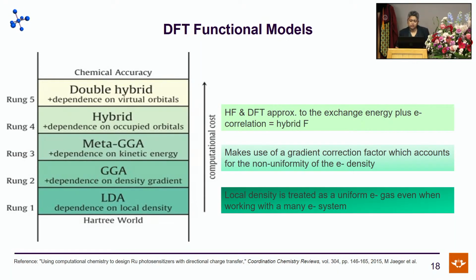Within DFT, we have different classes of functionals. And this is what you see on the slide here. On the left-hand side, you can see a ladder format, moving from LDA, GGA, meta-GGA, hybrid, and double hybrid. So LDA stands for local density approximation. What does this actually do? It actually treats the system to have a uniform electron gas, irrespective of the amount of electrons that we are dealing with. GGA stands for generalized gradient approximation.